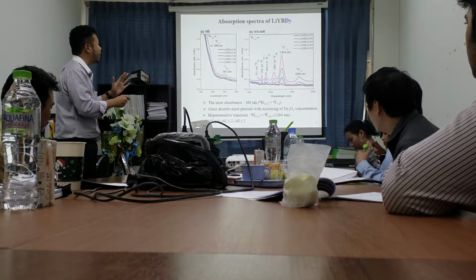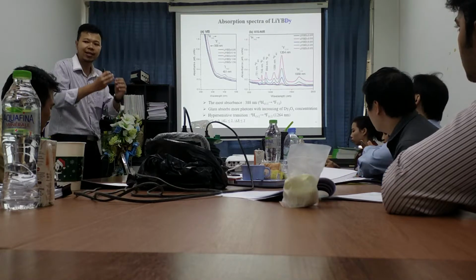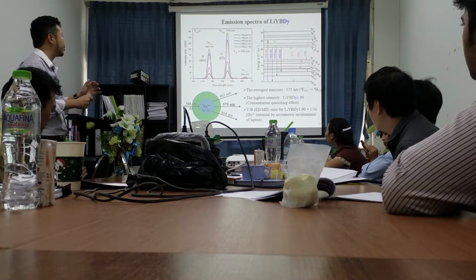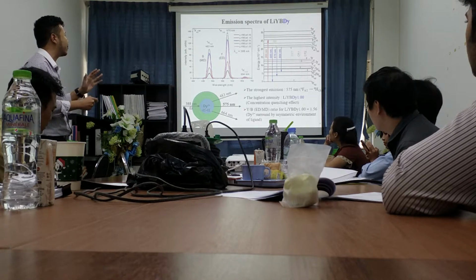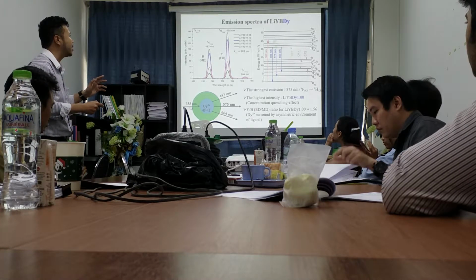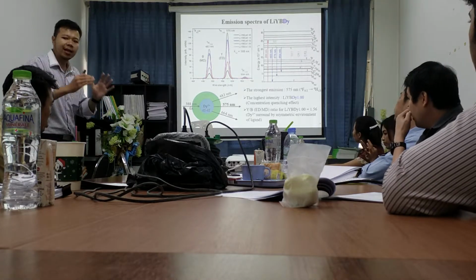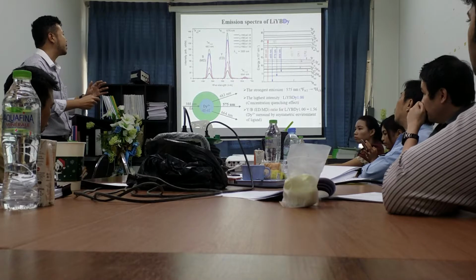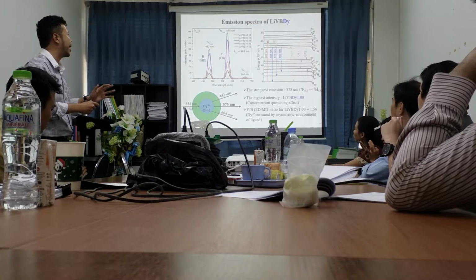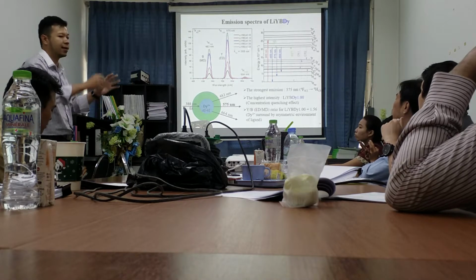Because the most absorbed band belongs to 388 nanometers, I chose this wavelength to excite the glass to study the emission spectra. We found three emission bands and the strongest emission is at 575 nanometers. The transition occurs from the luminescent level 4F9/2. And the emission intensity increases with increasing dysprosium oxide concentration from 0.5 to 1%. But for 1.5%, the intensity dropped because of the concentration quenching effect.